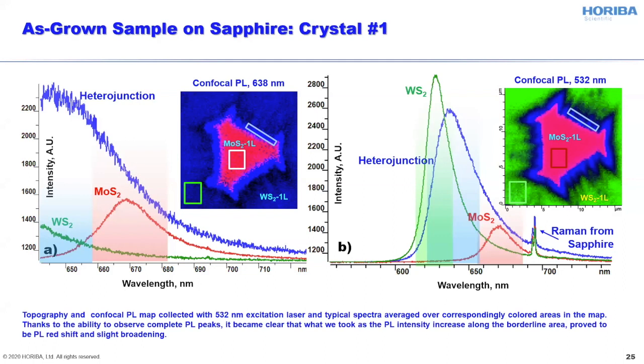tungsten disulfide. But the spatial resolution of conventional confocal microscopy, which in our case was about half a micron, is not sufficient to actually resolve what's going on at the nanoscale. And in order to probe the nanoscale distribution of the structural properties in this heterostructure, we transferred these crystals to gold following a recently published procedure.